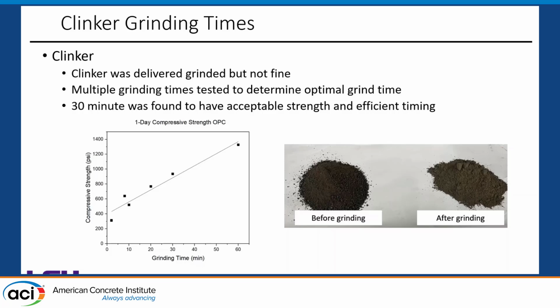We tried multiple different grinding times, and in general, the longer it was ground, the better. But we ended up deciding on a 30-minute grind time for the sake of efficiency. It was able to get a one-day strength of around 930 psi. And secondly, we didn't have to deal with the heat that you would deal with during long grinding times, and also just the timing efficiency.